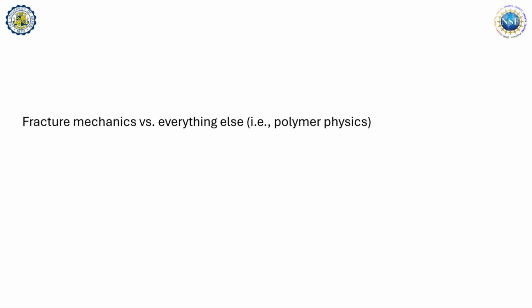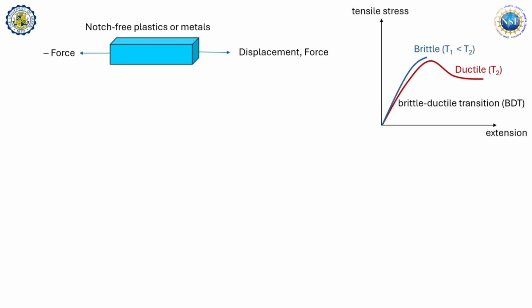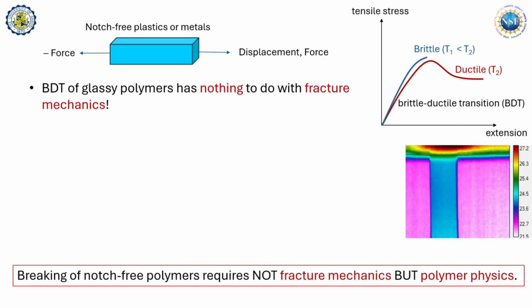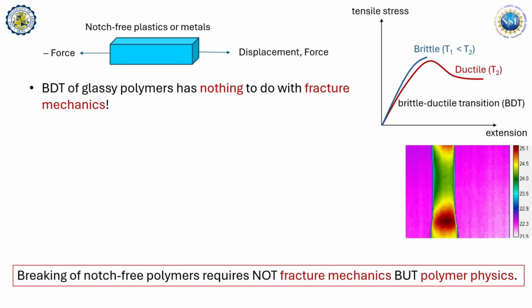My talk essentially is about the relationship between polymer physics and fracture mechanics. So I want to set the stage. When you have a polymer that's unnotched, it's generally either ductile or brittle. So if you do an extension, you'll find these 2 curves, either way. And polymer, miraculously, is capable of yielding. In other words, avoid brittle fracture. So for example, this temperature thing shows it can yield. But don't be confused. This issue of moving a few degrees, it turns brittle, we call the brittle ductile transition, is really not a subject for fracture mechanics. I want to indicate right away.